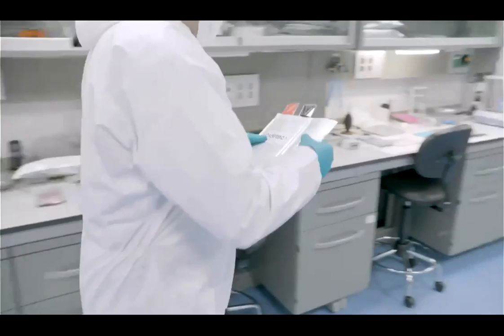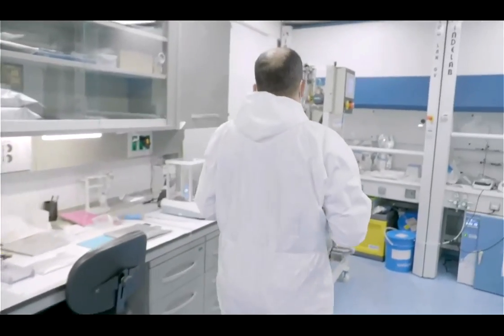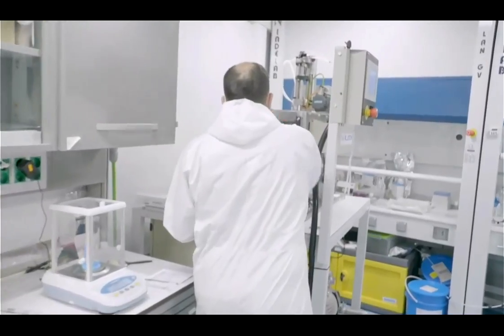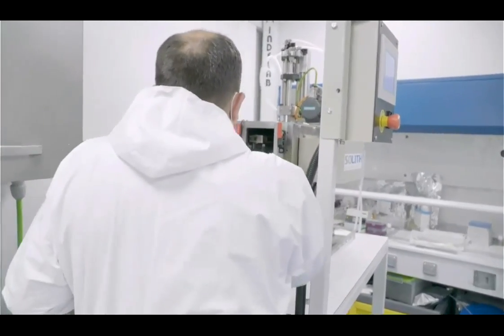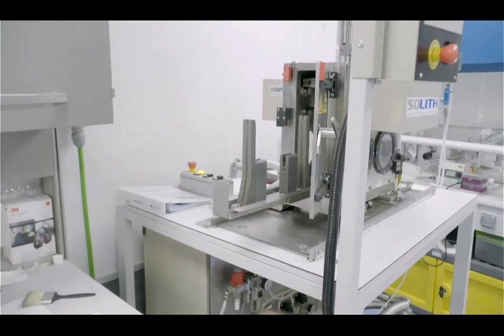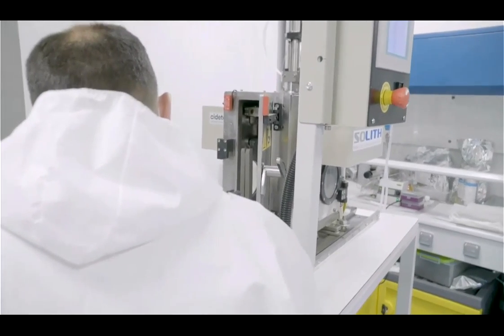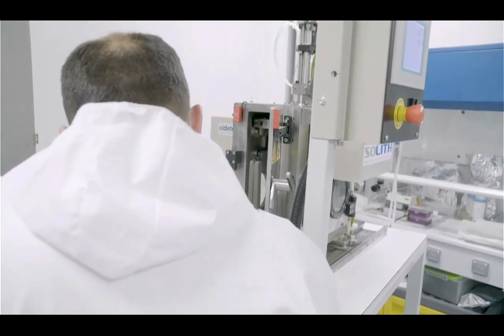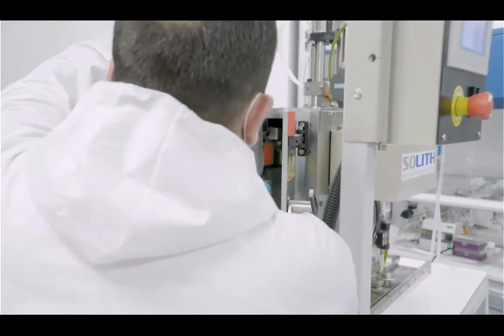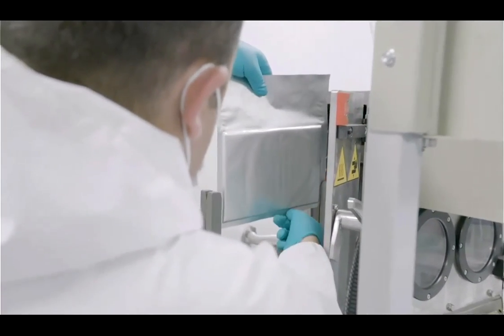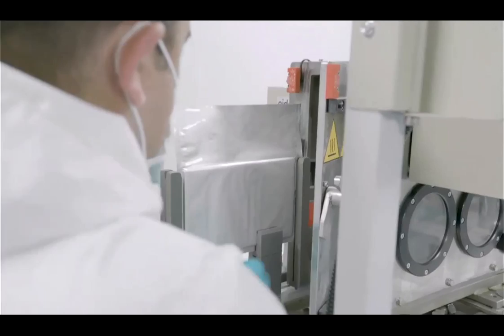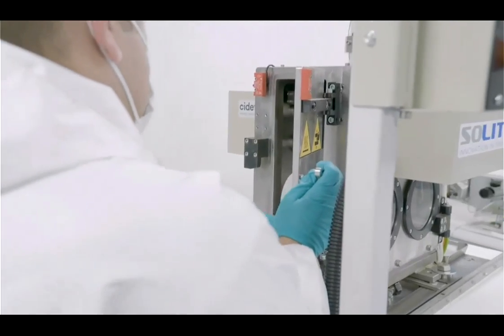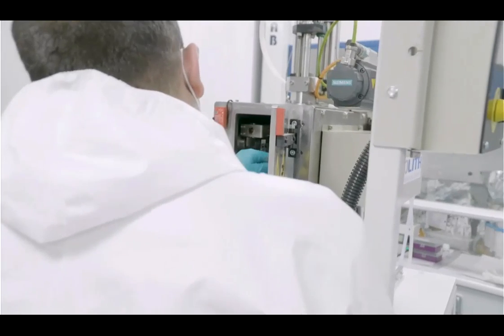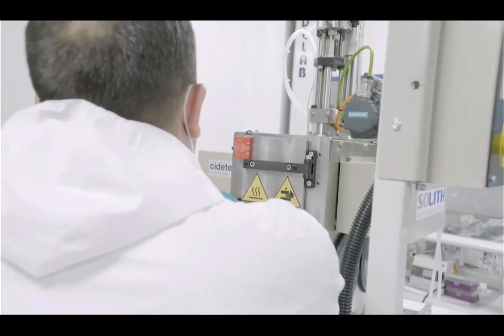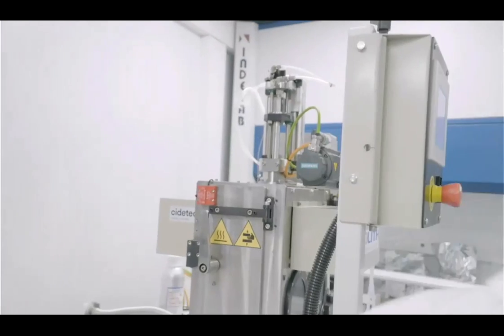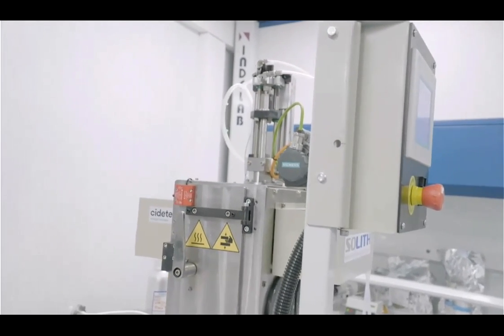Okay, we have prepared now a stack that is dry. So next step is the filling of the electrolyte that is done with the machine that you are seeing in the image. So here we have to distinguish between the filling of the electrolyte and the wetting of the electrolyte. Okay. So first step is the filling of the electrolyte. Iker is just putting the cell. It will introduce it in the machine, and the electrolyte will be filled into the cell under the vacuum using a needle and a high precision pump.